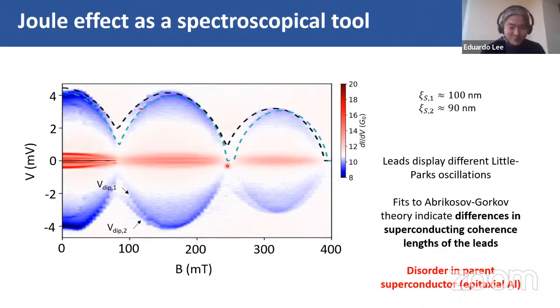It's true that if you completely kill heat dissipation by quasi-particles, so let's say we were able to go to zero temperature and there's absolutely no cooling by quasi-particles, then that would be the dominant mechanism. So this would be a correction to the heat dissipation that we take into account. Now, the very good agreement of that simple model, which doesn't take into account dissipation to the substrate, points towards quasi-particle diffusion being the main heat dissipation in the experiment. But what you said is not untrue. It's just that in the data we don't get such detailed information about dissipation to the substrate, as it's overshadowed by the quasi-particles. It's true that there could be inhomogeneities, or details there that play a role.